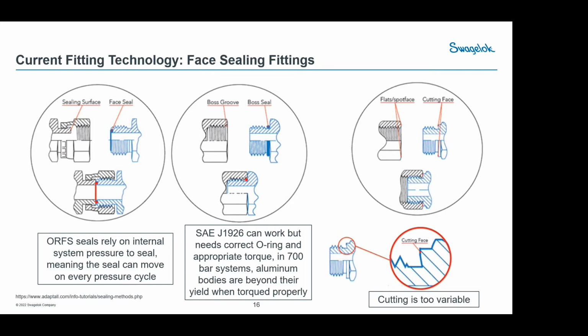So between the body and the fitting, you could get an O-ring failure, and the thought was that it was always an O-ring failure. What we found over time in some of the high pressure systems, and this is something to be careful about when choosing this fitting design, is that it wasn't actually the O-ring that was failing. What was happening was the load between the body and the fitting was being relieved. And what that meant is that if you didn't have a high load onto the shoulder, the pressure from the system would allow that fitting to actually start unscrewing itself.